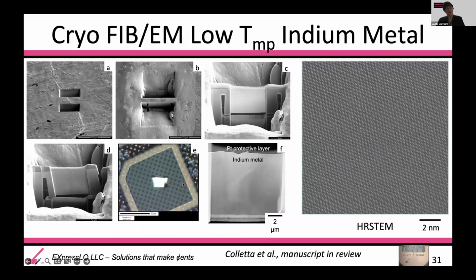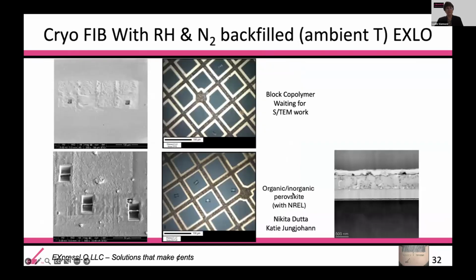This is the additional manuscript that we're working on. This is FIB milling of indium metal, so any low temperature metal or low temperature material that is going to be ion beam sensitive or electron beam sensitive. We can do the milling cold, we can do the imaging cold. There is no need to do the manipulation cold, and so this was all done in ambient conditions. Again, additional polymers, and this is an organic, inorganic perovskite with NREL, Nikita Dutta and Katie Jungjohann.